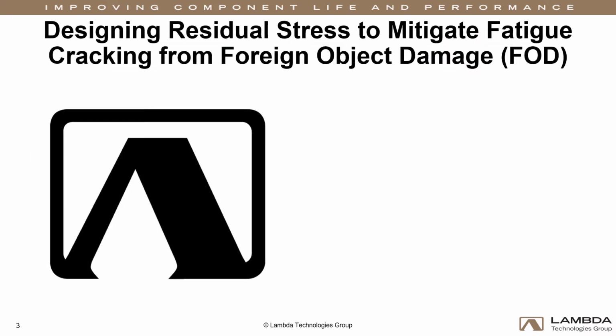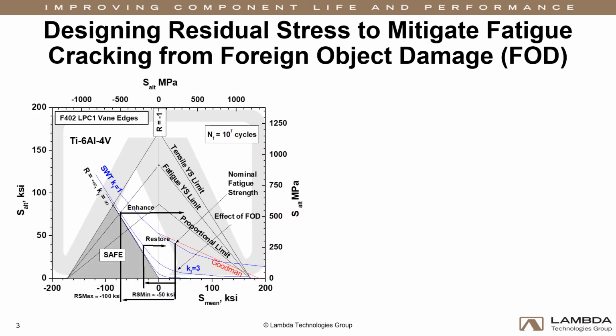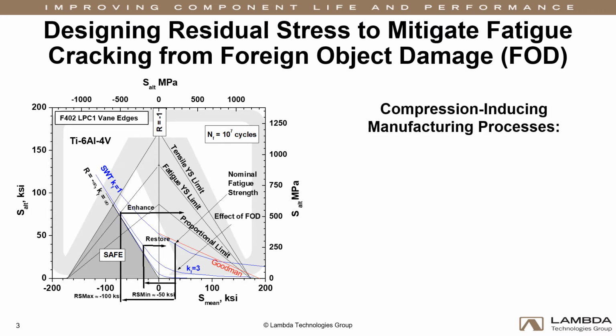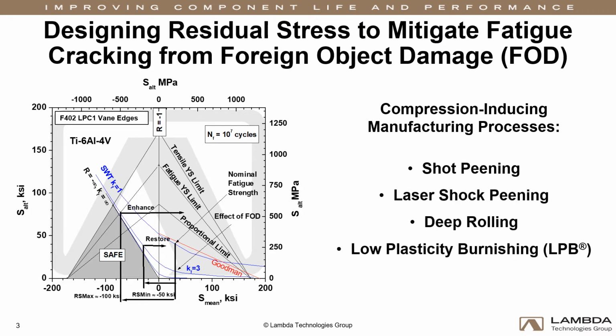At Lambda, we use designed compression to mitigate foreign object damage and extend component life. Introducing a layer of compressive residual stress deep enough to contain surface flaws from FOD mitigates cracking without having to alter either the component material or design. This can be performed through manufacturing processes such as shot peening, laser shock peening, deep rolling, and low plasticity burnishing.